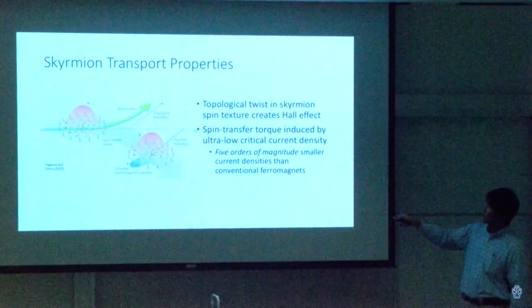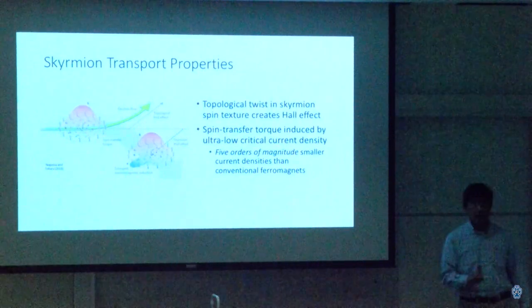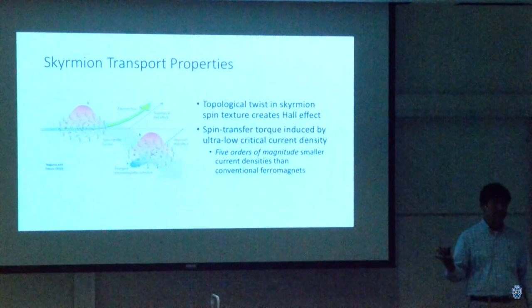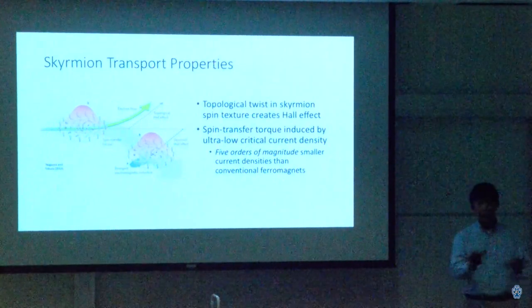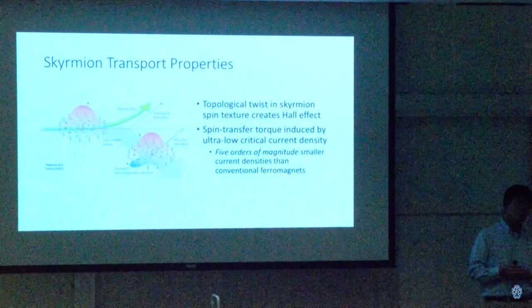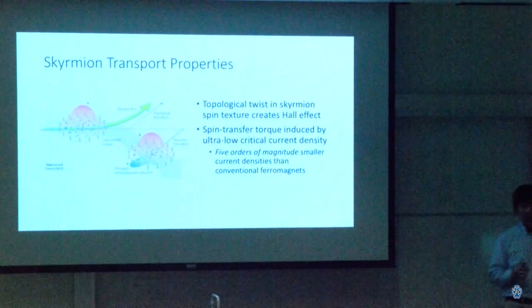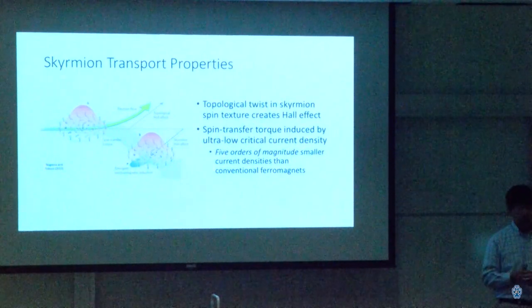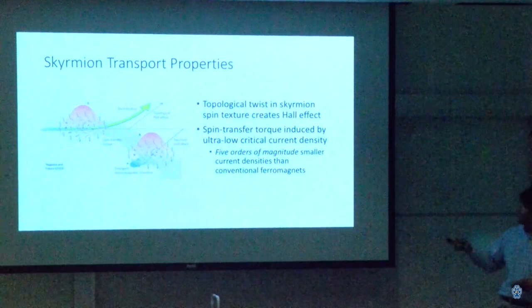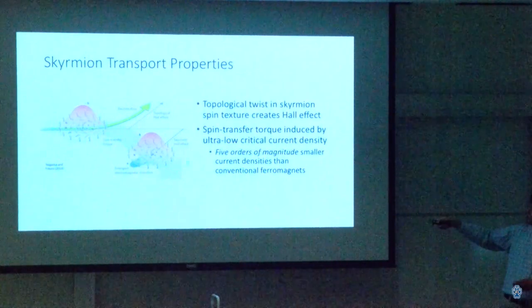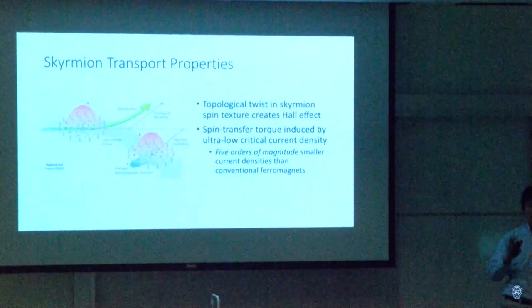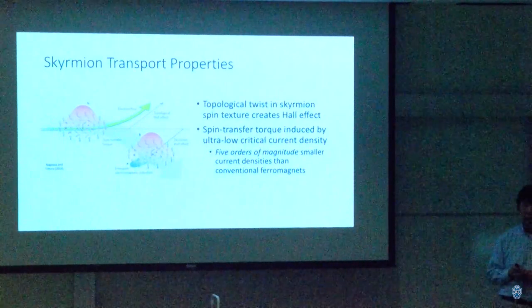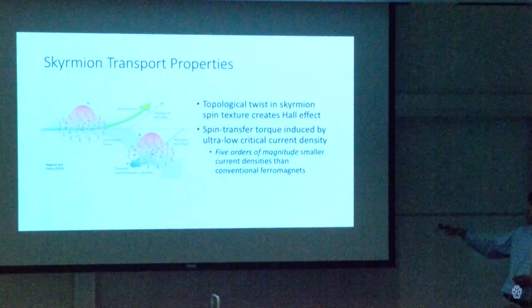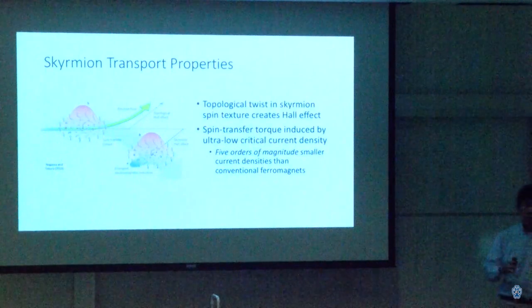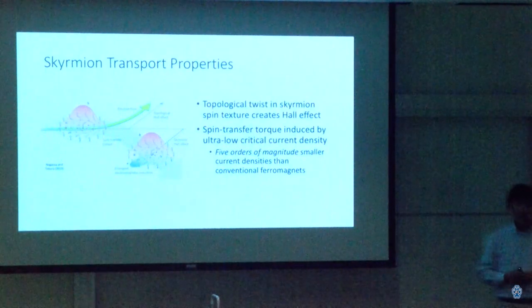This effect is what's also known as a spin transfer torque. You send an electrical current through a material and cause your magnetic spin texture to rotate or otherwise move. And people have demonstrated that with bubbles, but the theory indicates that skyrmions can be moved with a much smaller electrical current density than bubbles. As a matter of fact, 5 orders of magnitude lower than that of bubbles and conventional ferromagnets.